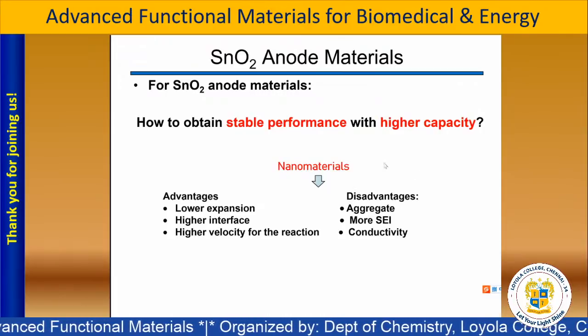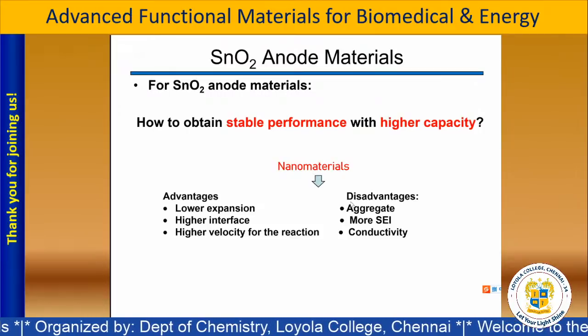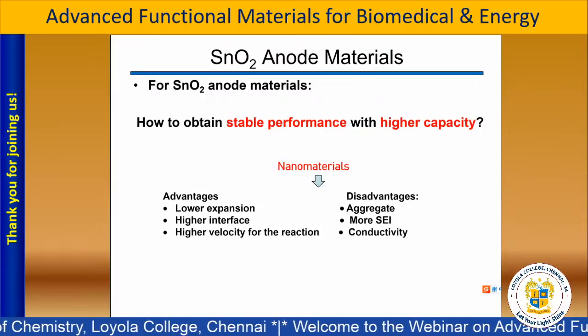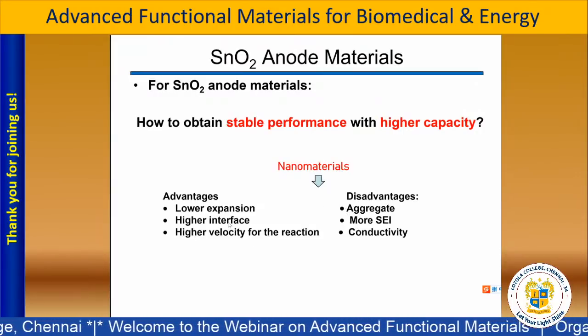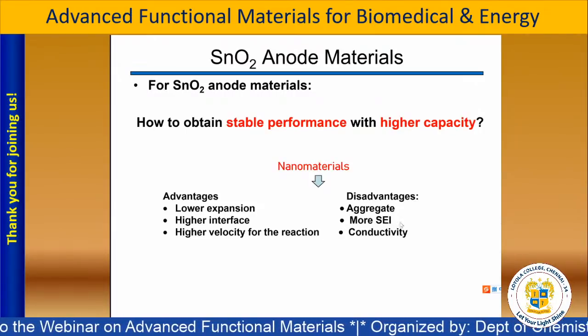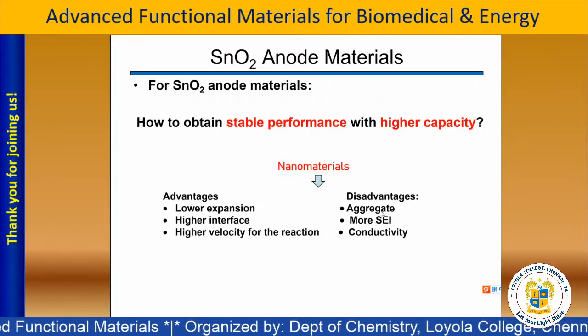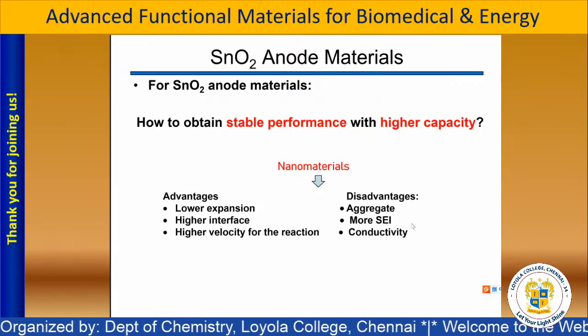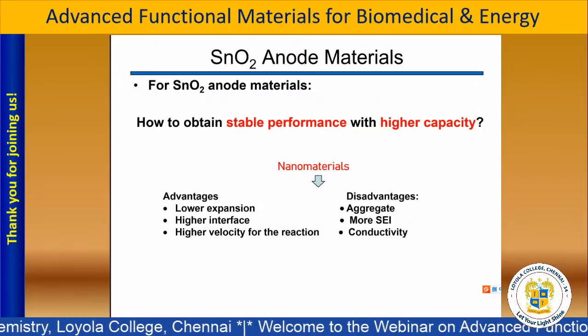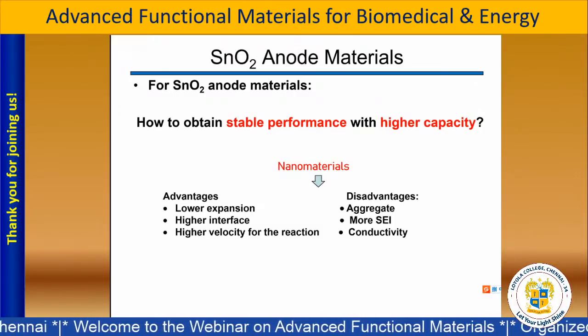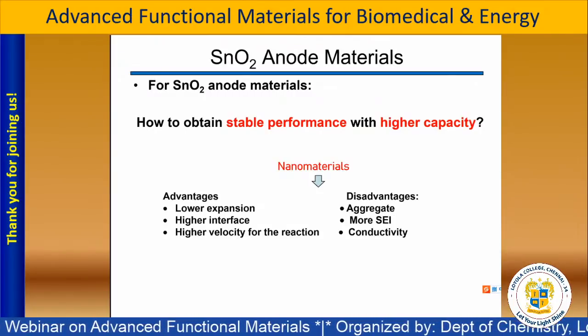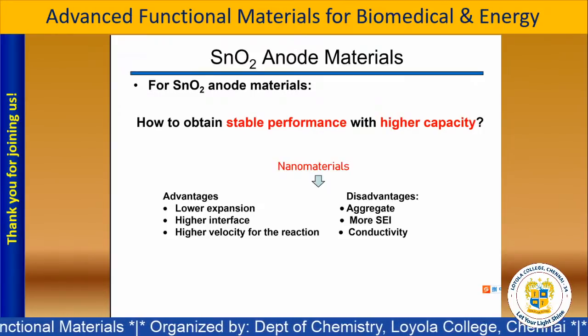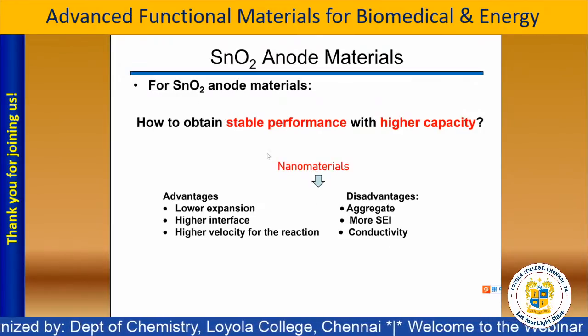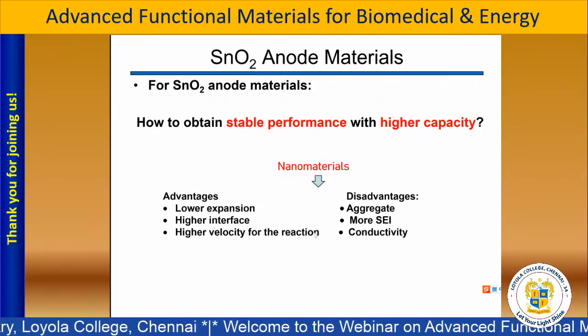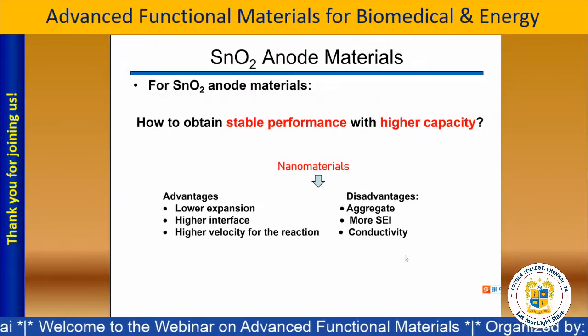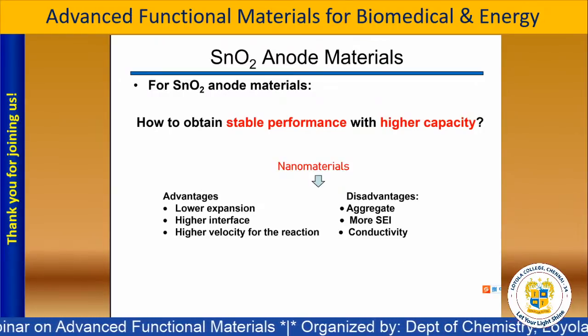Also, there are some new problems. Nanomaterial can reunite or aggregate when we use it. And because nanomaterial has a higher interface, more SEI may be produced. When the SEI is produced, more lithium ion will be wasted. So we don't want the SEI unstable. We want it to exist stably in the process. And the last is that even if we make the tin oxide nano-sized, the conductivity cannot be improved if we don't add some other conductive material.